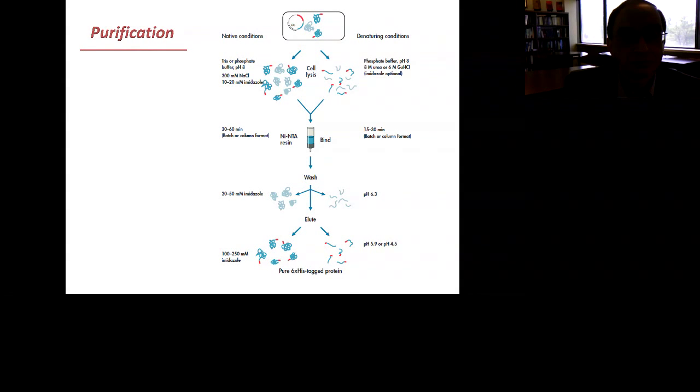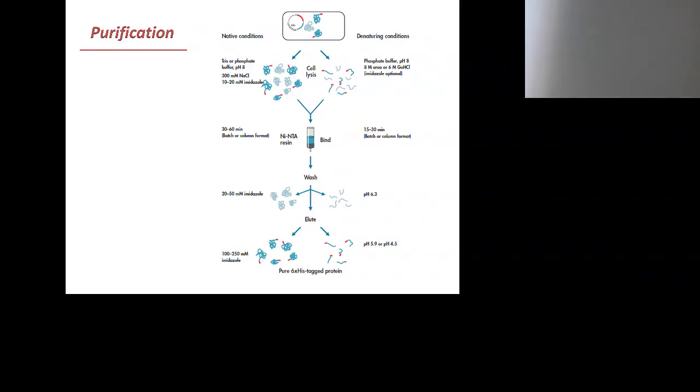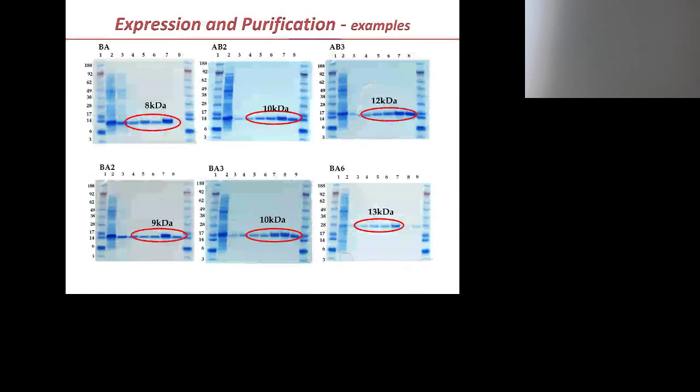That's why we have a histidine tag on the ends of these, although we have looked at some without the tag to make sure we understand the role of these in the assembly and properties. And as you see on this slide, we basically use a nickel affinity column, which is pretty standard, to get very good purity of these proteins. This is good for reasonably small scale purification. For larger scale, we have to use other methods, mainly because of just scaling issues and costs. But when we're done with this process, we then have a very pure set of proteins we can use in the processing work in Joyce's lab. And obviously, this is all embedded with the modeling guidance work with Markus's lab.